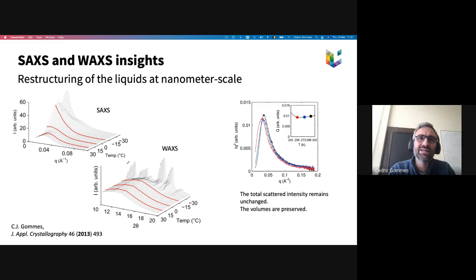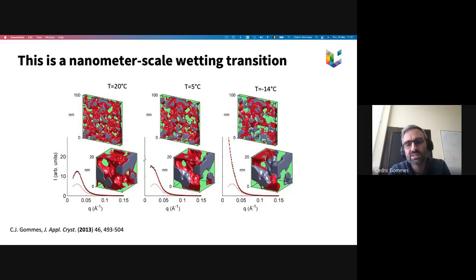nitrobenzene. And interestingly, the area under these curves is related to the volume of the scattering phases. So this area under these curves in the end is relatively constant, which means that the liquids are restructuring, relocating inside the pores, but not changing in volume. So they're not dissolving. So in the end, using these stochastic methods that I just mentioned, you can try to reconstruct the liquid configuration of the liquid as a function of temperature.